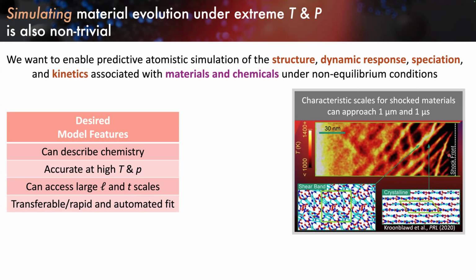It's left in its wake these yellow striations that are localized regions of enhanced disorder, so nominal shear bands, that also happen to be thermally activated. It's within these features that the chemistry that ultimately gives rise to a detonation event can nucleate.